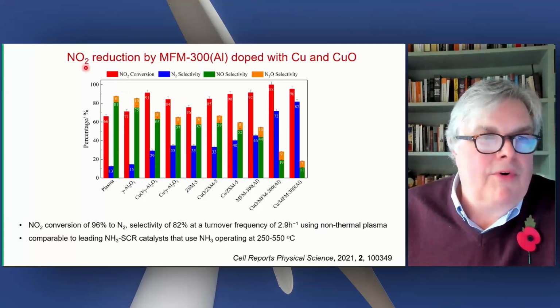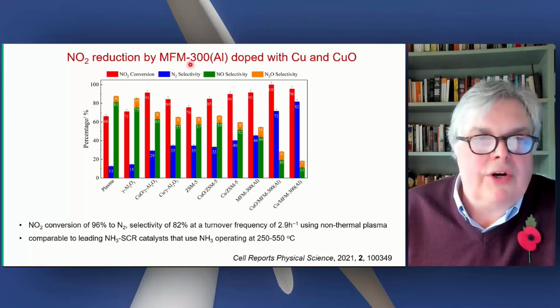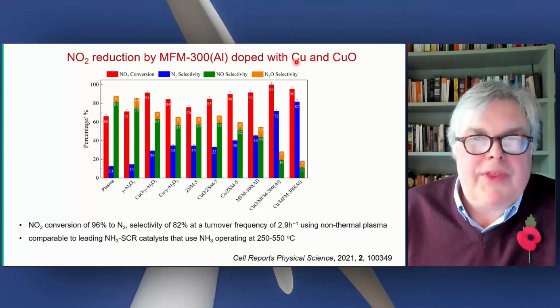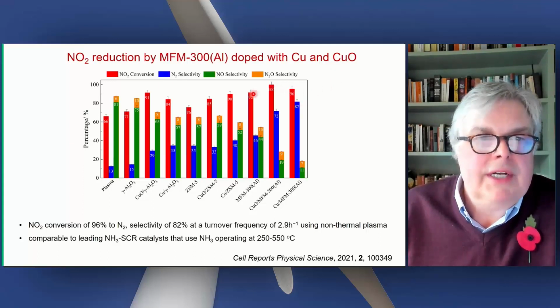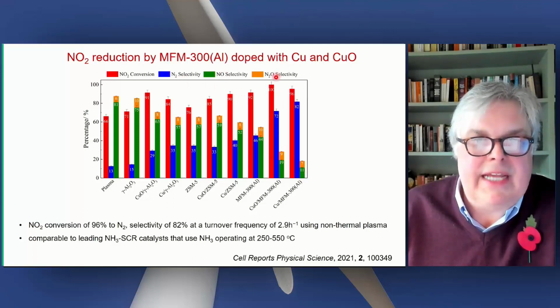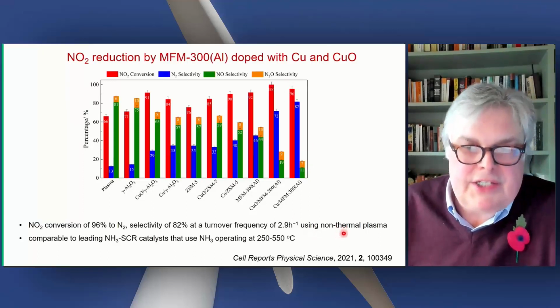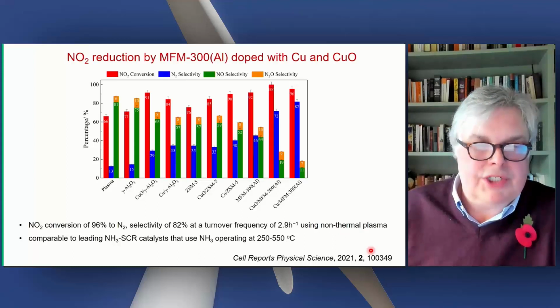Here is a summary of a recent paper we published on NO2 reduction to dinitrogen. So this shows dinitrogen selectivity using a doped aluminium MOF, doped with either copper metal or copper oxide, and it's showing very good NO2 conversion to dinitrogen selectivity. There's the NO selectivity and N2O selectivity. Under, I emphasize this, non-thermal plasma conditions.